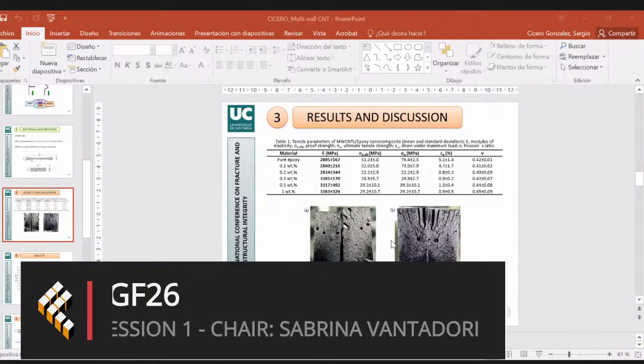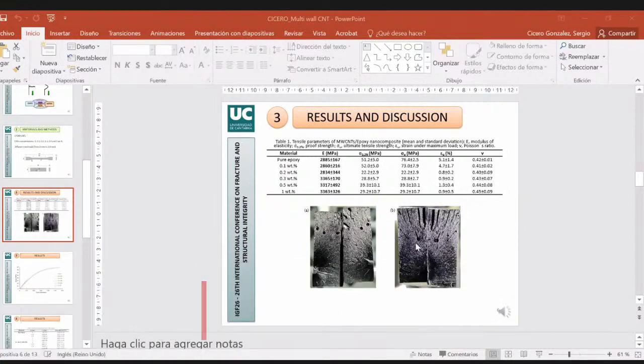Okay, perfect. The points are pores. And the lines, you mean these ones? This is the fracture direction, basically, fracture marks. But the important thing here is that these are pores, so the material is not valid for our research purposes. And this happened for 0.2% upwards.